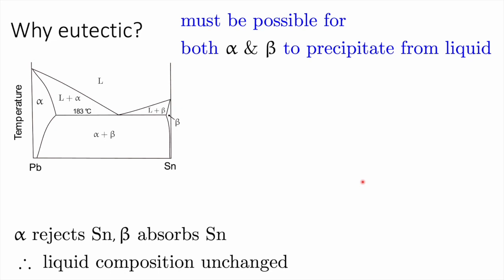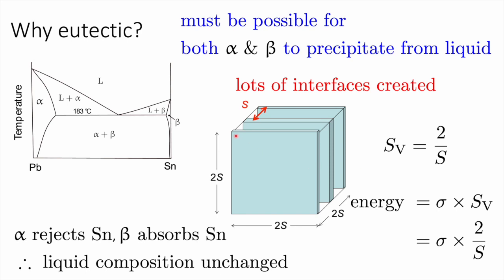Now, the second point actually opposes a eutectic reaction, because in the process we are creating lots of interfaces between the alpha and beta. So here I'm taking a very simple view of the eutectic mixture, where we have a cube with a side 2s, where s is the interlamellar spacing between, say, the alpha phase in the eutectic. So inside this cube we have two interfaces here between alpha and beta, one interface here between alpha and beta, and another interface here between alpha and beta.